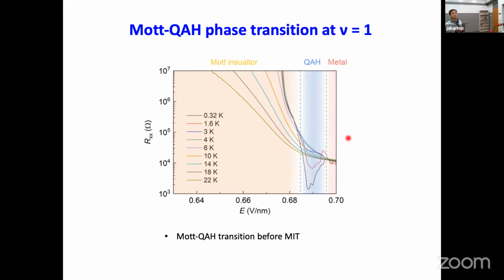At an even higher electric field, it actually turns into a semi-metal. At lower electric field it is a charge transfer insulator, which is topologically trivial, so the resistance just diverges with decreasing temperature. So everything is tuned by an electric field, going from a charge transfer insulator to a Chern insulator, and then to a semi-metal.